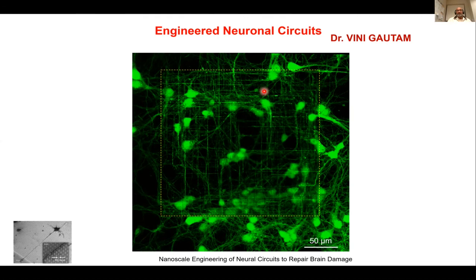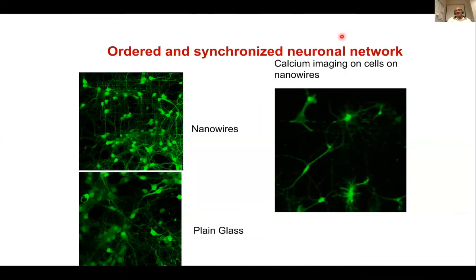So what Vinny does is something called calcium imaging. She puts in a calcium dye. As and when the neurons are firing action potentials, calcium ions are passing through the ion channels, and the concentration of the calcium ions will determine the intensity of the fluorescence light coming out. She takes a video of this and tries to correlate, if this neuron is firing, what's happening to this neuron and these astrocytes and a wide variety of structures. And she compares this with neurons grown on nanowires and neurons grown on plain glass substrates, which are typically used by neuroscientists, so that we can compare these two.